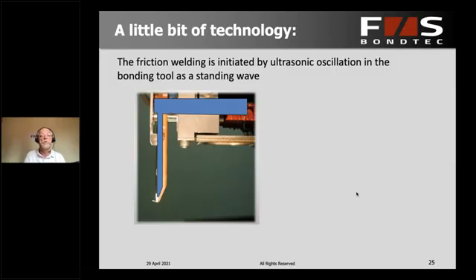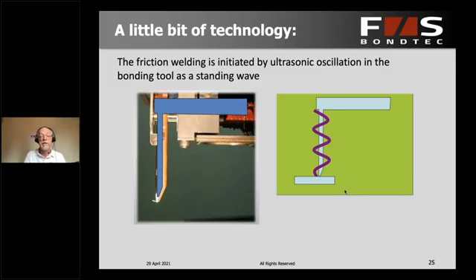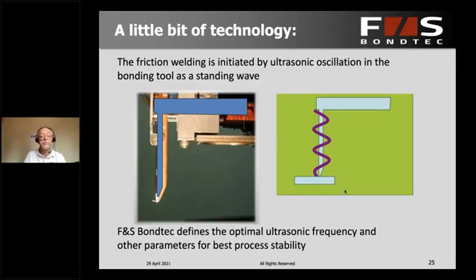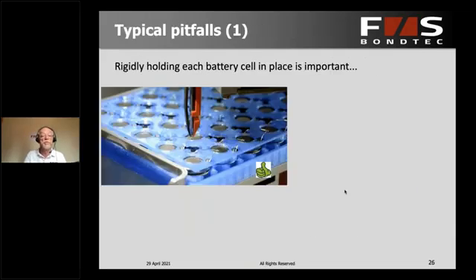To go a little bit further into technology, friction welding is, and what you see here is really the business end of our bonder. Friction welding is initiated by an ultrasonic oscillation in the bonding tool, very much like a standing wave. So we need a very precisely defined resonance frequency to run all of this, but this is really our job. And once the process is all set up, then we have an extremely stable and extremely robust process that for you is just a question of switching on and switching off.